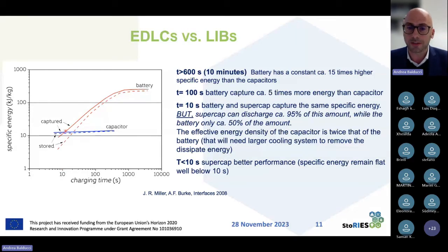But what is the big difference is that supercapacitor can discharge more or less 95% of this amount. So the two lines, the two blue lines are very close to each other, while the battery can only discharge 50%. So what is the message of this figure? That when you are now in the time frame of 10 seconds, the supercapacitor is working in a much more effective way than a lithium-ion battery, for example.